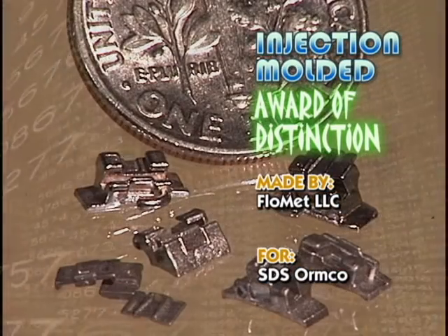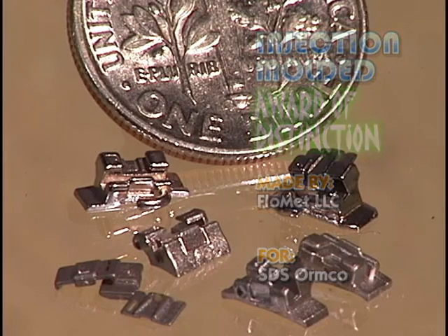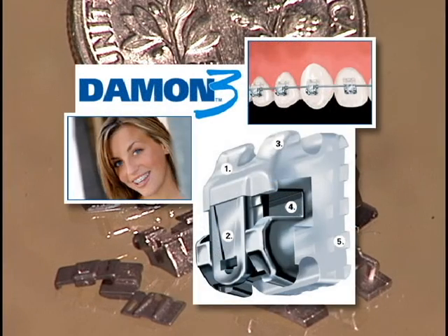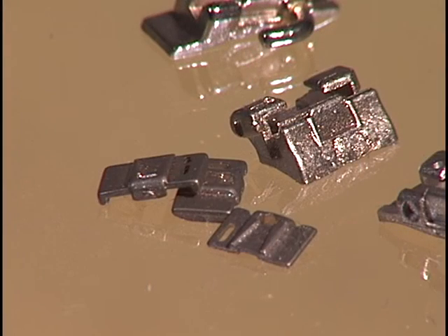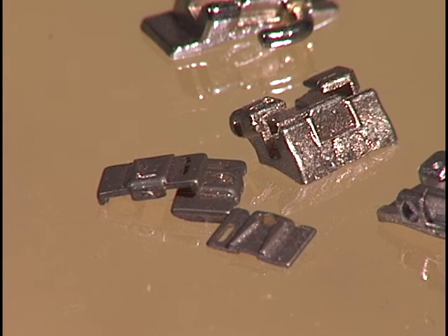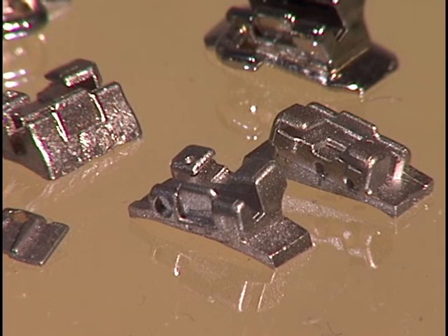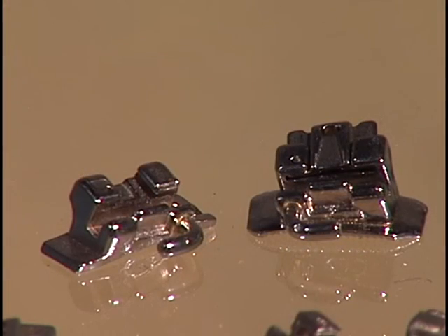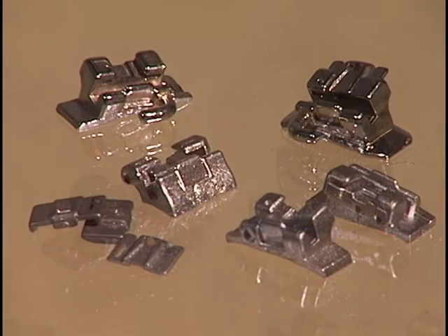FloMet LLC and its customer SDS Ormco have won an award of distinction in the injection molded category for a Damon 3 molar buckle tube system used in orthodontic braces. The system consists of multiple parts made from 17-4 PH stainless steel. The parts have an ultimate tensile strength of 120,000 psi and a yield strength of 104,000 psi. Elongation is 10%, and the heat-treated hardness range is 38 to 42 HRC. The heat-treated ultimate tensile strength is 185,000 psi, and the heat-treated yield strength is 160,000 psi. The tube system was first introduced in the all-metal Damon self-ligating orthodontic appliance. When in full production, this application will total more than 12 million parts annually.